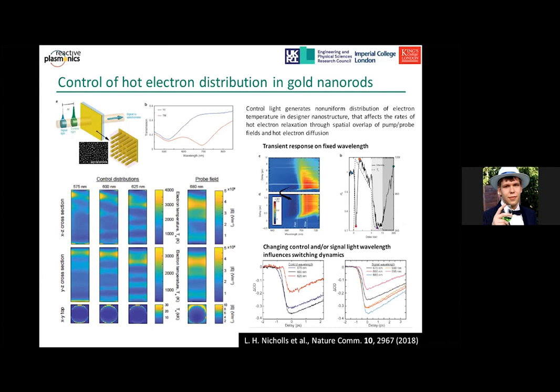This gives us an additional degree of freedom to control, for example, by tuning either pump wavelengths or probe wavelengths in a fixed structure, we can change how the hot electron population overlaps with optical modes and control the mentioned above polarization switching by using that. So as shown here in the bottom of the slide, with either tuning the pump or probe wavelengths.